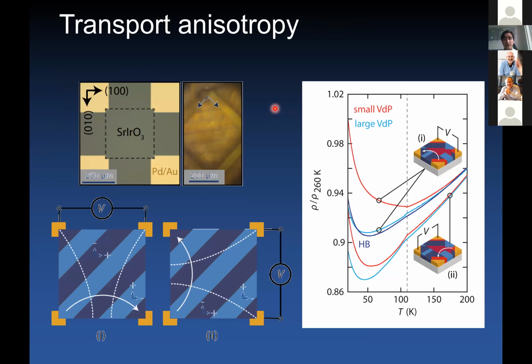A second interesting transport phenomenon that is observed is a very strong transport anisotropy that occurs at the structural phase transition. If you fabricate a transport device made, for example, as a van der Pauw type of square, where you have your contact current and voltage probes at the edges of the square, you can inject your current and detect voltages in different directions in your sample. You can switch your current and voltage probes systematically across this type of structure. And then you can orient your current in different directions with respect to the tetragonal domains that you observe in your sample. So this is an optical microscopy image of one of our devices.